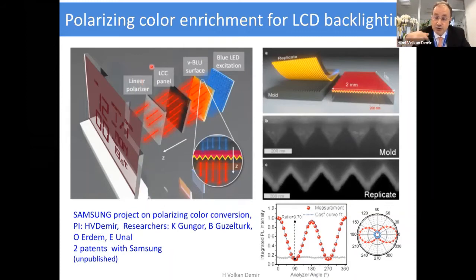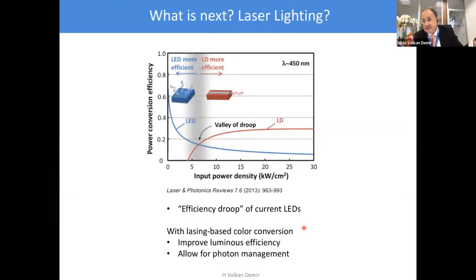Here, the idea is to do the color conversion while you generate the right polarization you want and suppress the one you don't desire. And that's what we showed together with Samsung that created two patents co-owned by Samsung. And here you can see, in addition to the color conversion with spatial features, these are all nano features, we can actually suppress one polarization and induce only the one of our choice. Of course, for us, the question is what is next? And this is really important as scientists like myself, what is coming? We think both in lighting, especially high-end lighting, but also in certain cases, display-like applications, laser-based lighting will be critical.